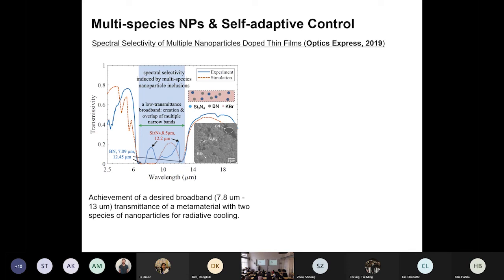But how to do that? If we can find more than one material, and each of them could emit a narrow band, and if they overlap and share the common wavelength range between 8 and 13 microns, we might be able to achieve a broader band window. That was my idea, and we demonstrated it experimentally. We found two nanoparticles, silicon nitride and boron nitride, and the host material, the matrix, is KBr, potassium bromide. This is the first time we studied more than one species of nanoparticles.